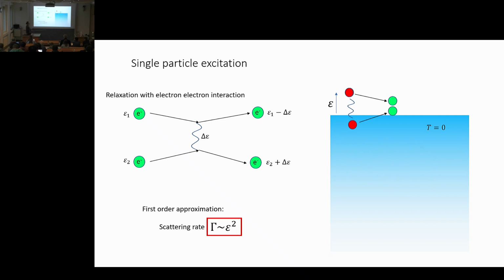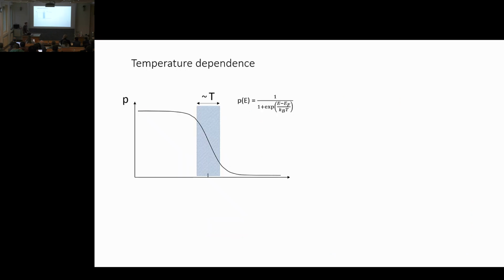And also the available phase space to scatter into is, again, it needs to be above the Fermi sea, whereas within the Fermi sea, every state is occupied. So we have 2 factors of epsilon. And our scattering rate is proportional to epsilon squared.